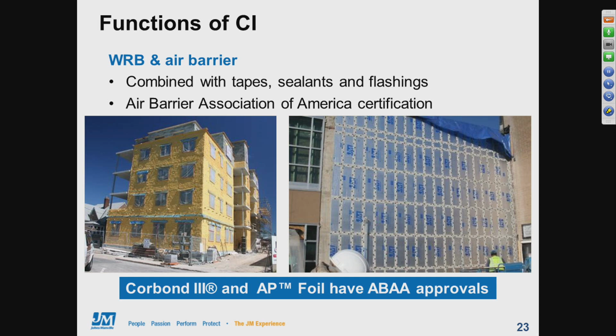So as we talked about earlier, foam sheathings and exterior spray foam can both be used as water-resistive barriers and air barriers. Foam boards have to be combined with tapes and sealants, and all the materials need to integrate with window and door flashings to be able to do this. An example would be the photo on the right. Really, the important thing here is to look for assemblies that have Air Barrier Association of America, or ABAA, certification. Both Johns Manville's AP foil-faced foam sheathing and our Corbond III spray foam products have passed all of the testing required for ABAA approval, and our websites have all of those certifications and details.